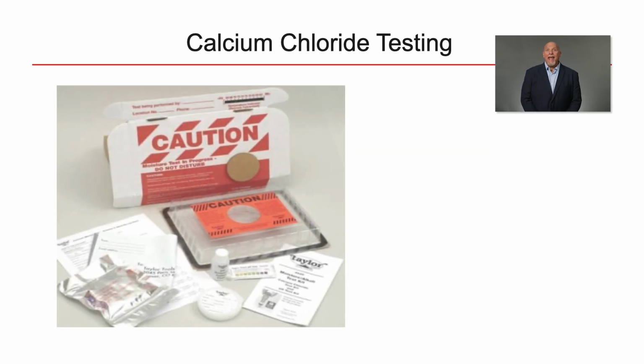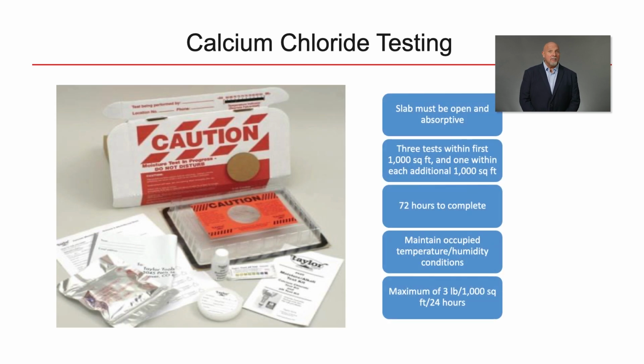ASTM F1869, standard test method for measuring moisture vapor emission rate of a concrete subfloor using anhydrous calcium chloride, is a commonly used test in the United States for measuring the moisture content at the surface of a concrete slab. It is a simple test that, when performed properly, will yield a pounds of moisture vapor transmission per 1,000 square feet value. Most floor coatings have an acceptable value of 3 pounds per 1,000 feet.